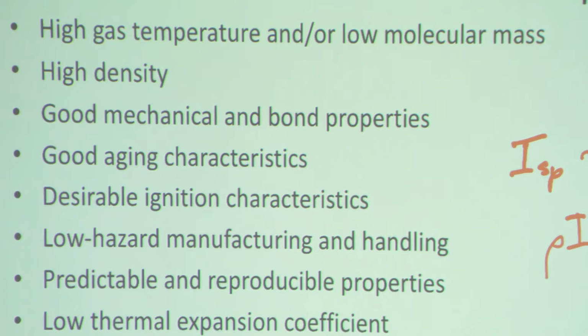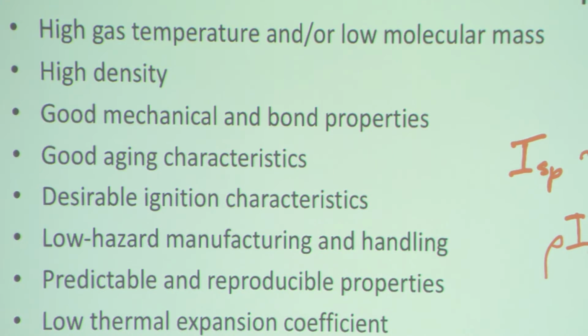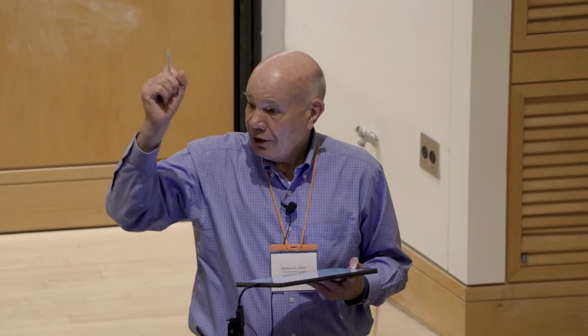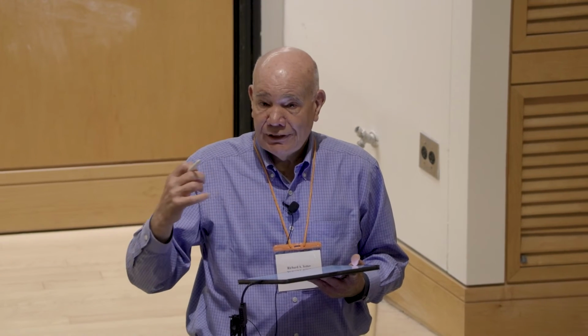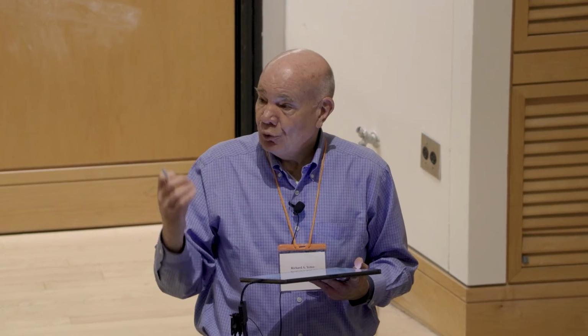A good mechanical and bond properties. One of the things that differentiates, again, explosives and propellants is that in an explosive, the mechanical properties aren't too important, whereas in a propellant, the mechanical properties are very important. I need to make sure I know where the burning surface is all the time, okay? And under the G loading, say in a rocket or something like that, I can have a lot of strain. And that strain can actually start to de-wet the particles in the binder and create void spaces.